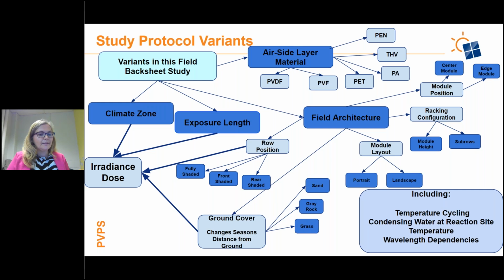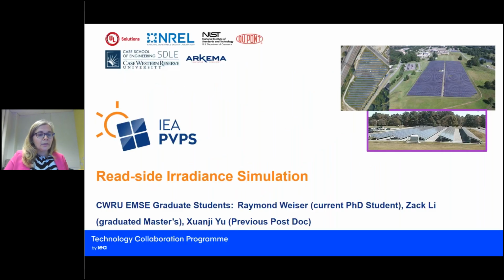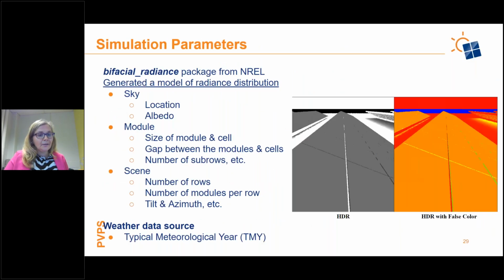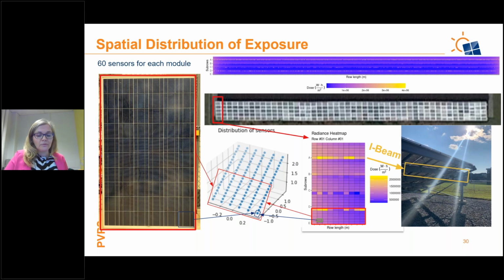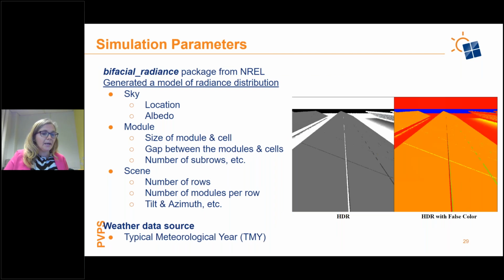And the idea here, one of the things we really need to consider in our fielded modules is that irradiance is definitely impacted by ground cover. So gray rock is impacting albedo. Grass seems to really decrease it. Roads are increasing degradation. And also the distance to the ground is something we started measuring for these modules. And also we started looking at how much water was sitting on the backside of the module, how much dew point was there. So I'll quickly go through. We started simulating how much irradiance was on the backside of the modules with NREL's bifacial irradiance package.